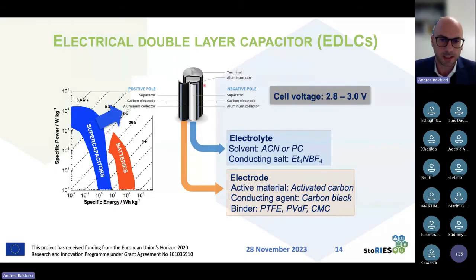Like in a prismatic battery, also here you have a layered, let's say, structure in which you have a positive pole, in which you have an aluminum current collector where you have coated the positive electrode. Then you have a separator, which then is impregnated with an electrolyte, and then this separator is dividing the positive from the negative electrode, which is again an electrode of carbon, coated on an aluminum current collector. The materials, and we will see in detail later, used for the electrode as active material, we are using activated carbon, as a conductive agent carbon black, and as a binder PTFE, PVDF, or CMC.